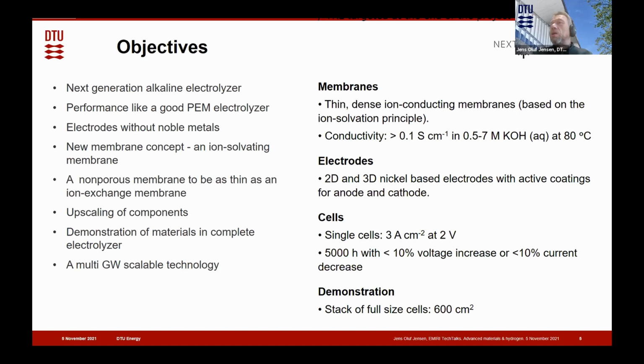And the more specific objective is for the membranes, we are going for conductivity that is beyond 0.1 Siemens per centimeter at 80 degrees. This is a membrane that will be fully immersed in potassium hydroxide. We are looking at different concentrations, but probably we're going to have quite a high concentration in the end. So that way it will be very similar to the known alkaline electrolyzers, just with a lower internal resistance. The electrodes we're working with both 2D and 3D. DLR has a very good technique for making electrodes on plates to provide catalytic layers, but we are going into the 3D regime and developing that by a variety of different processes.